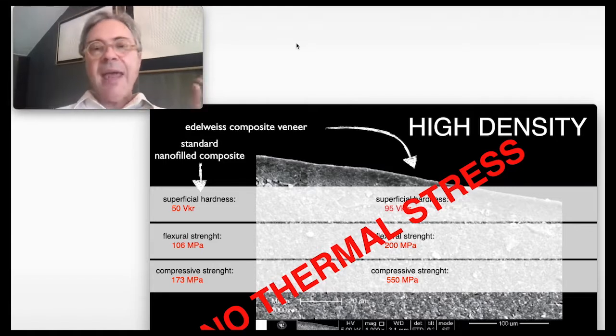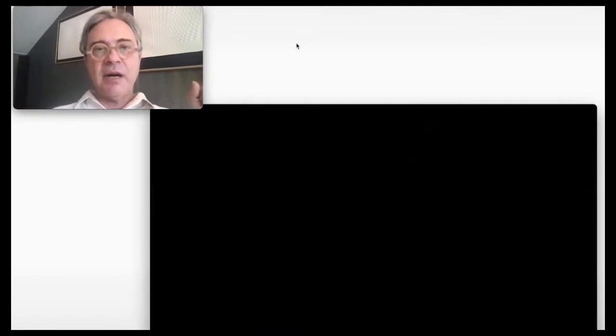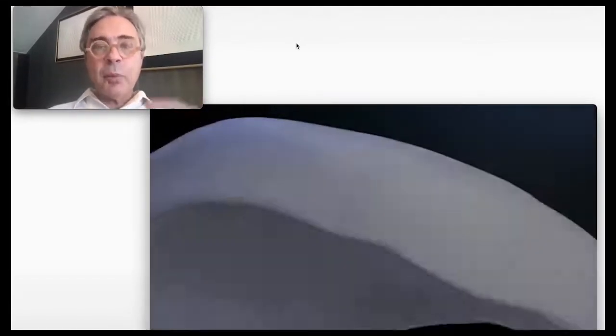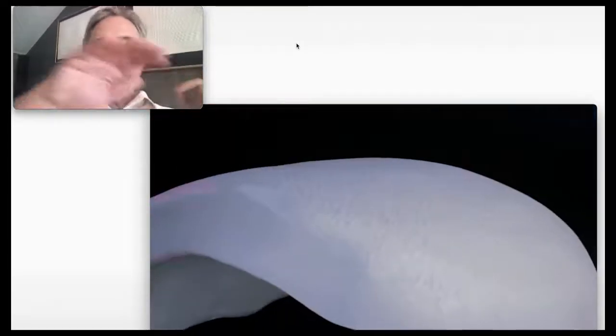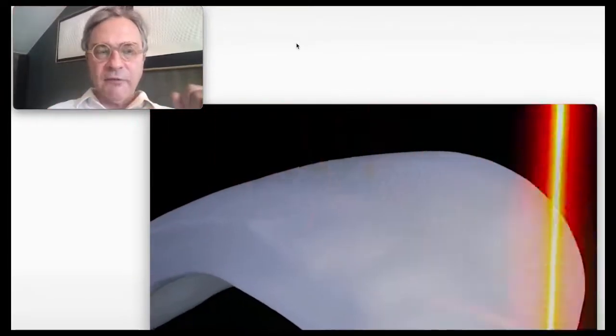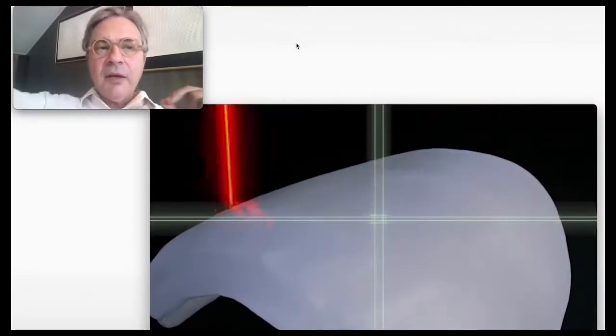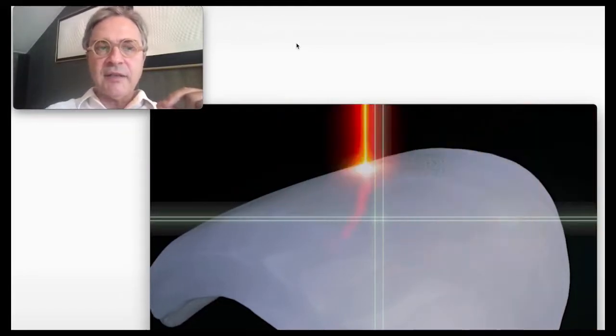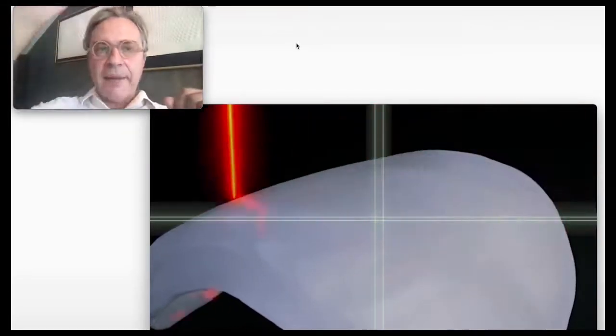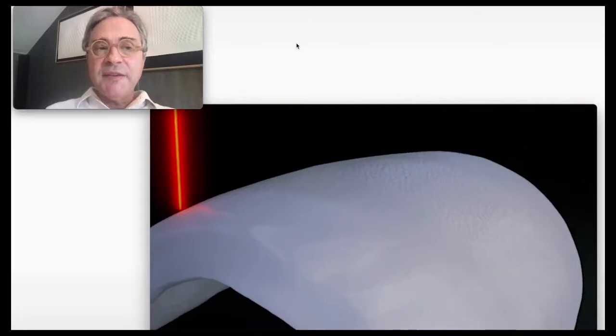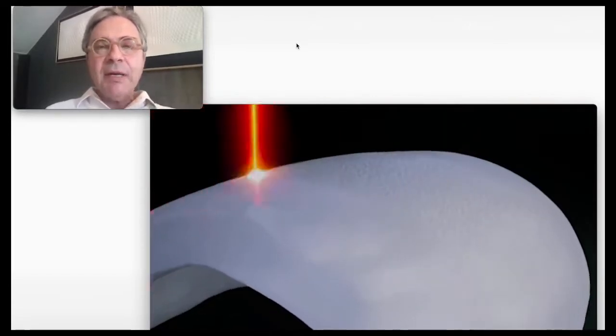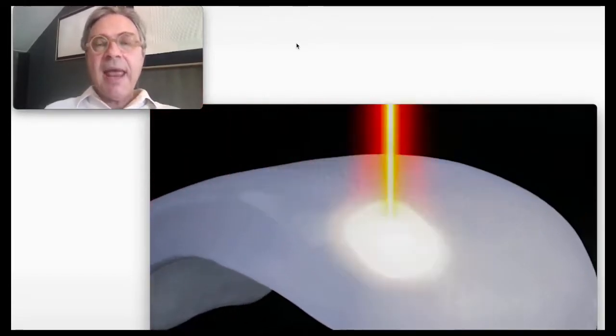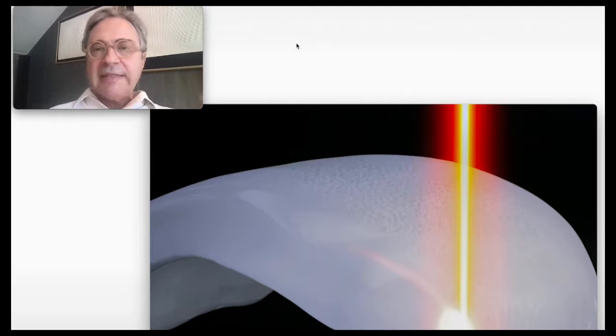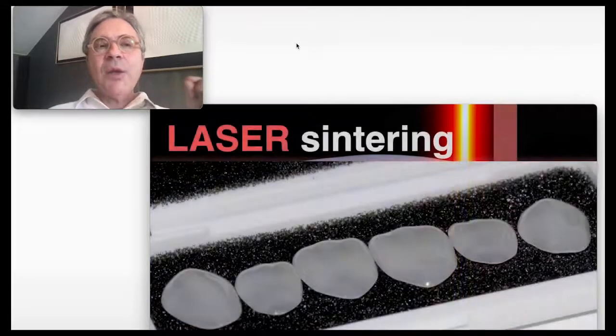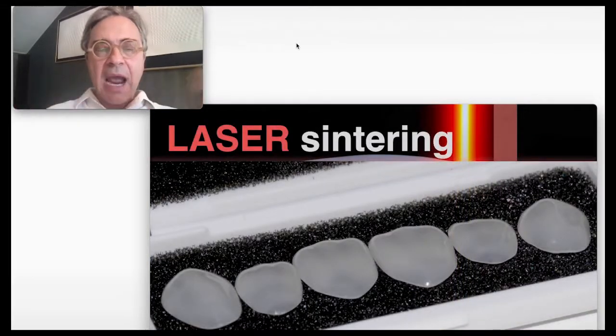300 degrees, and then laser sintering starts. Edelweiss veneers are processed with a sintering laser that goes back and forth on the surface of the veneer. The laser beam goes through the entire thickness of the veneer and bounces back. So it's actually a double sintering, and the sintering laser evaporates the resin and melts the filler. So what you have here now is a 100% inorganic composite restoration, melted filler.